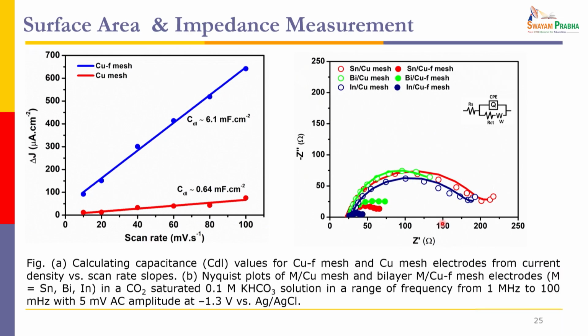We've also done some more electrochemical studies as confirmation. This is a foil, and this is after a foam is made. This is the copper mesh as such, and this is the copper mesh on which a foam of copper was made. You can see there is a change in the slope, a change in the value, which indicates that this has a high surface area compared to the copper mesh. We call this the electrochemical surface area. So that means this can give high activity.